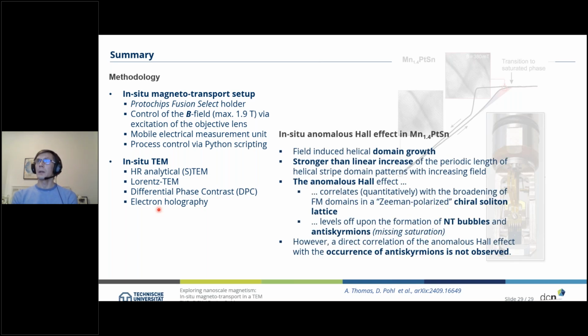For the manganese platinum tin system, I showed to you that we have an induced helical domain growth, which is stronger than a linear increase, which stems from the chiral-soliton lattice which appears. The anomalous Hall effect can be correlated with this chiral-soliton lattice, and it levels off upon the formation of non-topological bubbles and anti-skyrmions. However, there was no direct correlation of the anomalous Hall effect with the occurrence of anti-skyrmions. So from our point of view, it seems not that we can measure or see a topological Hall effect in that system.